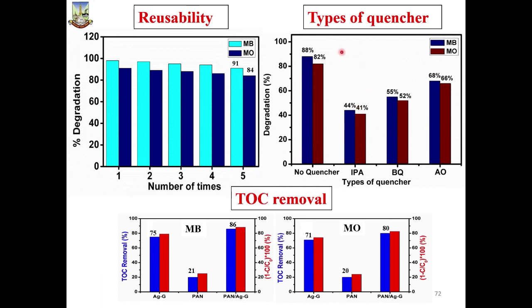With respect to the different organic radical quenchers, without quencher it is 88% and 82%. In case of AO, or when we compare with the other quenchers, 68% and 66% degradation is there. We have done the TOC removal study also for methylene blue and methyl orange. In case of silver graphene sheet it is 75%, PAN 21%, PAN AGG 86%, whereas for methyl orange it is 80%.